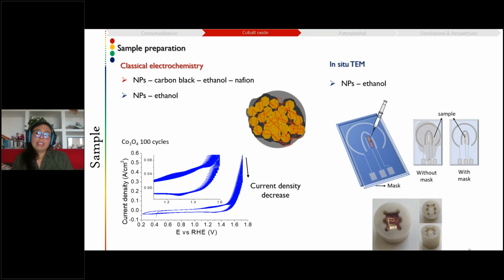But the second thing is, when you put your sample, you just cast a drop and it will go all over the chip. And of course, that might create some short circuits, or it will spread all over, and we wanted to limit that. So for that, we created a mask that allows us to put our sample only on the surface of our window. And this allows us to make sure that the current that we were measuring was coming only from our window. I know that nowadays there are very specific techniques for the sample preparation, where they use micro sampling to put specific amounts over the electrode. This is what we had at the time. We figured out a way to put it only on the window.